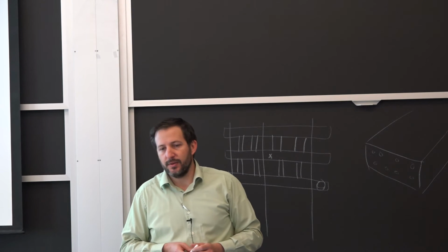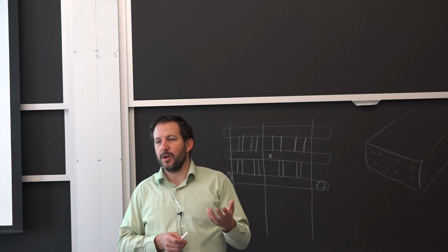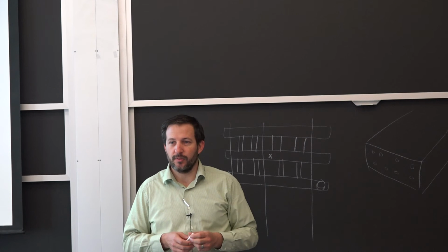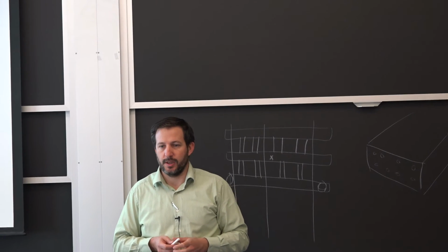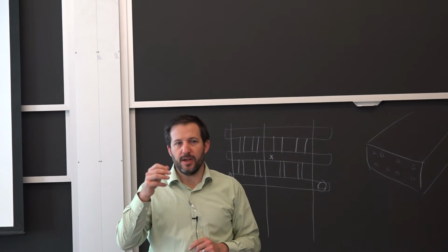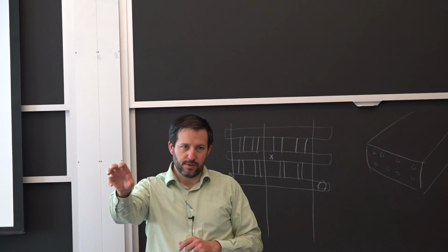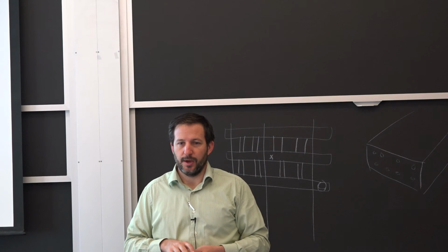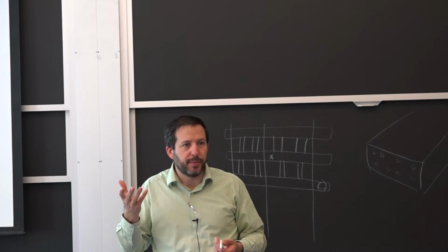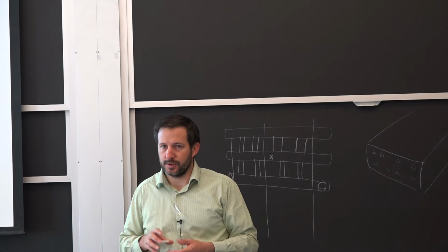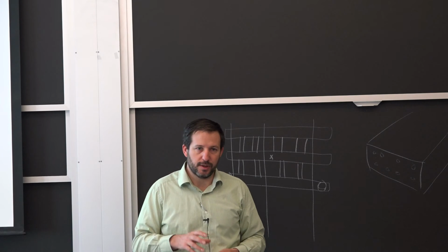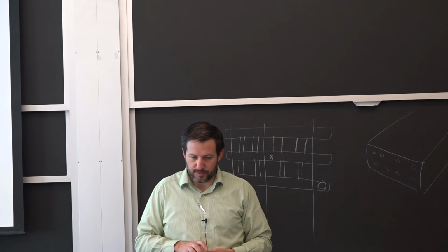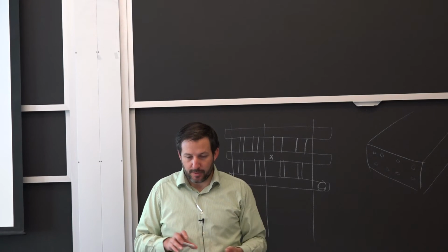So you can think of this, let's say we're talking about aluminum for an aircraft. The pH is not too far from neutral, even if you're on the coast, but then you start thinking, maybe I'll have a little salt deposit on the surface of the aluminum. So locally, I'm going to change the conditions. And that's where the pitting really starts, in a lot of other conditions too, just by locally changing it and having enough potential to break the natural oxide. So it's unfortunate. Can't make everything work.